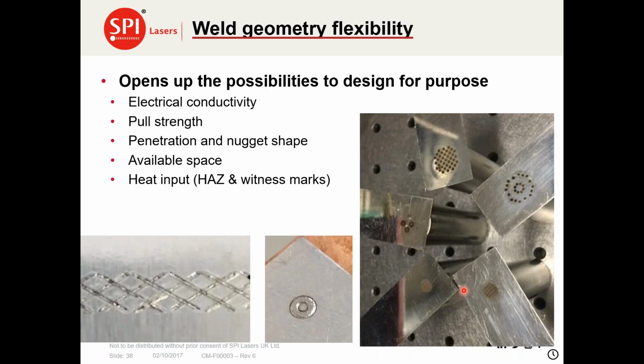Again, it opens up huge geometrical flexibility, and we can design for purpose. So if we want electrical conductivity, we look at area. We can design for pull strength, for penetration, based on the available space, and also on whether we are conscious of having a witness mark or burn through on the second plate. And one of the things that we can do is weld quite thicker plates to thinner plates, even when the thicker plate is copper, for example.